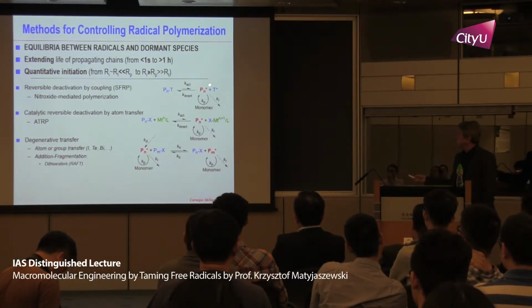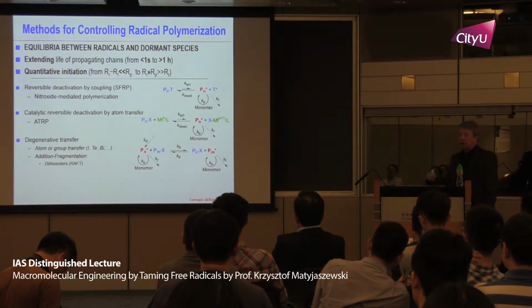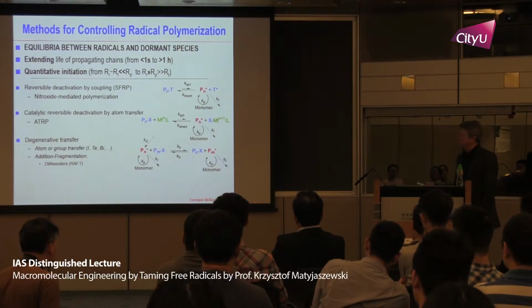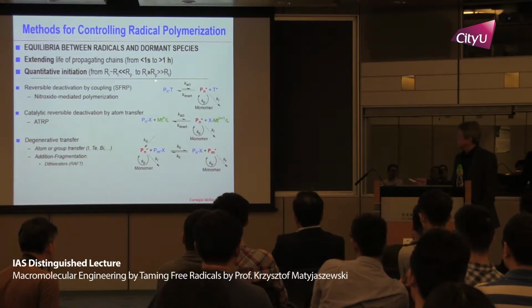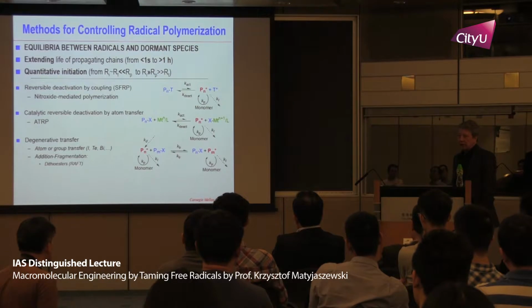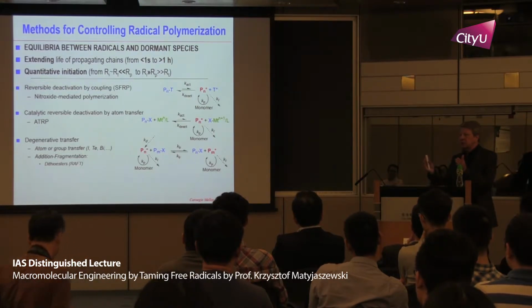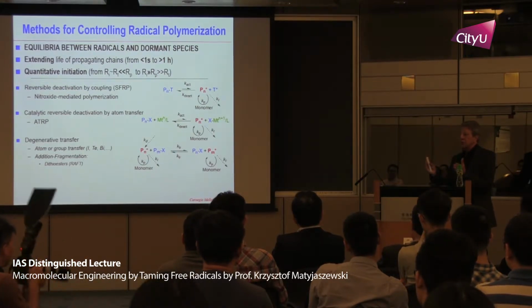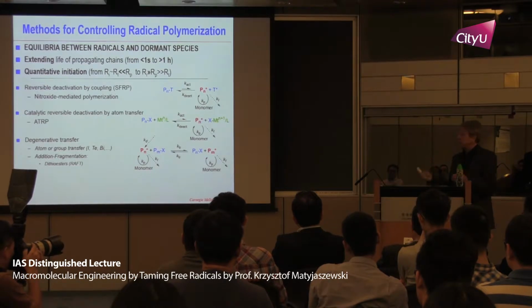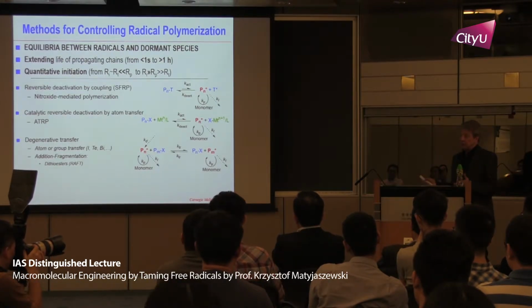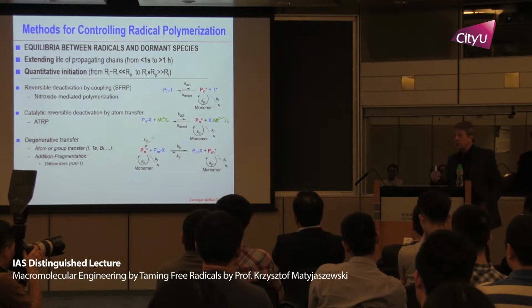So in that case, this would be cobalt porphyrin. And then you can make a cobalt organometallic species exactly like vitamin B12. But in all of these cases, you need one of these species per chain end. If you want to make a short chain, degree of polymerization 10, it means it should be 10 mole% of cobalt porphyrin, very expensive. So we wanted to make something cheaper, maybe using something as simple as chlorine or bromine, but